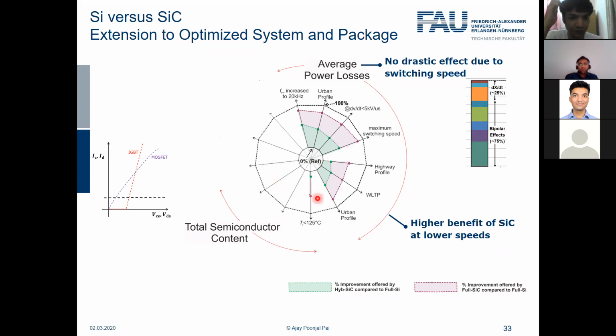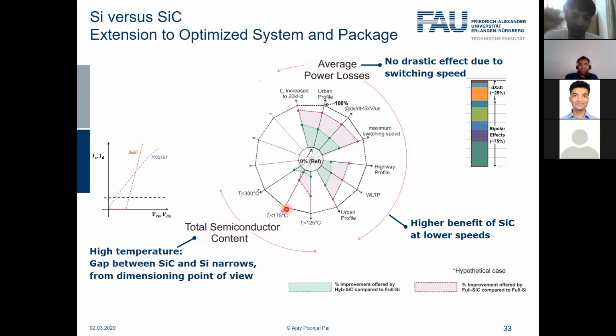So now what happens instead of restricting the junction temperature to 125 degrees Celsius? What happens when I restrict it to, let's say, 175 degrees Celsius here? So we see that the benefit of silicon carbide actually goes down. Instead of 50% lower chip size for silicon carbide, now you will have only 30% lower chip size compared to silicon. And like I said, silicon carbide for the same area is not the same cost as silicon. So there is also a cost or price difference.